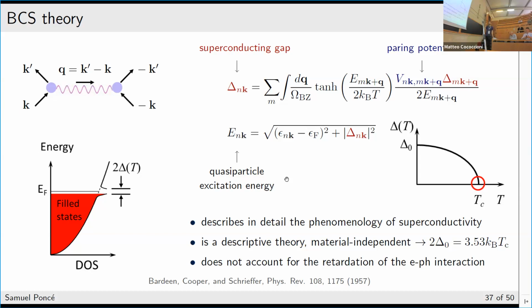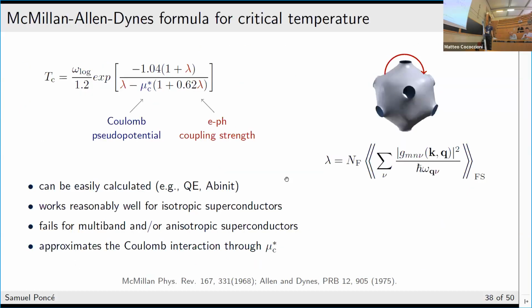And also, it doesn't account for retardation of the electron-phonon interaction. And so the idea is to go to maybe a more refined theory. But staying with this sort of phenomenological theory, I just want to mention that this is also a very used formula to compute the critical temperature. This is called the McMillan-Allen-Dynes formula. And it's quite easy. It allows you to estimate the Tc.